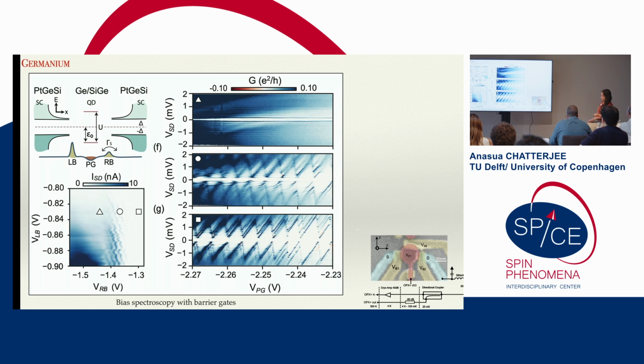So we do have this center dot that we can proximatize, and you can destroy that with magnetic field. But what is also encouraging is that by changing this right barrier, we fix the right barrier, left barrier, and we move the right barrier. And you can see that even by moving the barrier you go from a superconducting state to a quantum dot Coulomb blockade state. And this is pretty nice because you want to be able to do this switch with a gate rather than by using a magnetic field, which, for instance, you can't pulse. So that's a nice result, and that seems to work.